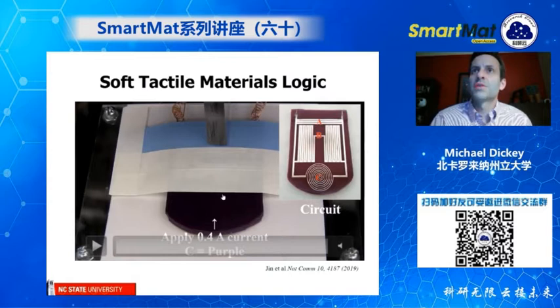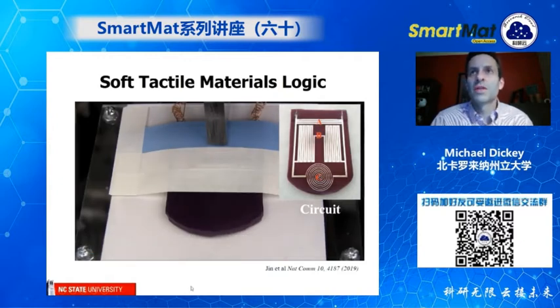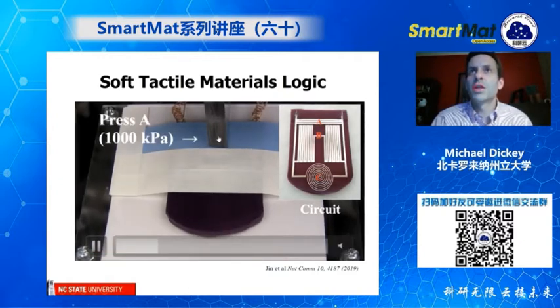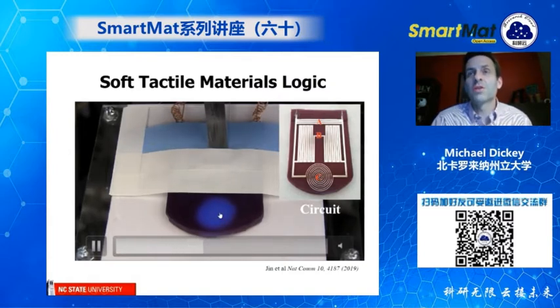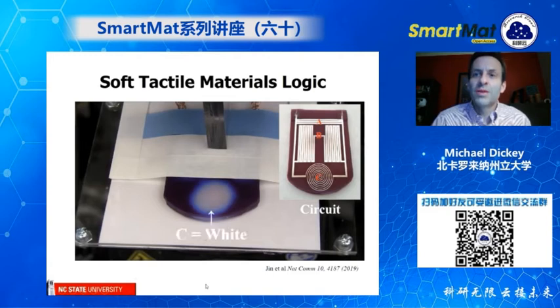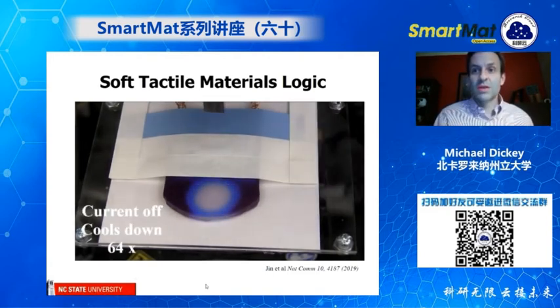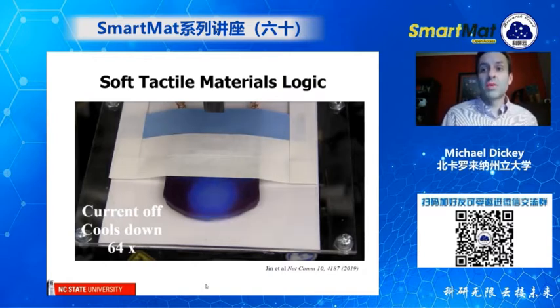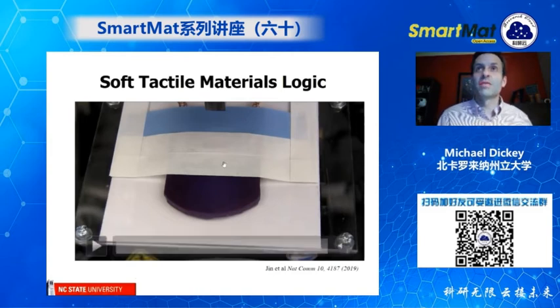And we turn it over, so this is region C, and we run current, and the current goes through A, B, and C. And so in region C, there's not enough current to cause a color change. But if you push in region A, that redirects the current here, and you get enough current to cause a color change. If you push A and B, you get a different state. So again, there's no transistors here. This is just silicone and liquid metal. And all we're doing is, based on how we make the circuit, we can do very, very simple logic. You can think about it as like a 0, 0, 0, 1, 0, 1, 1, 1, 1, or something like that.